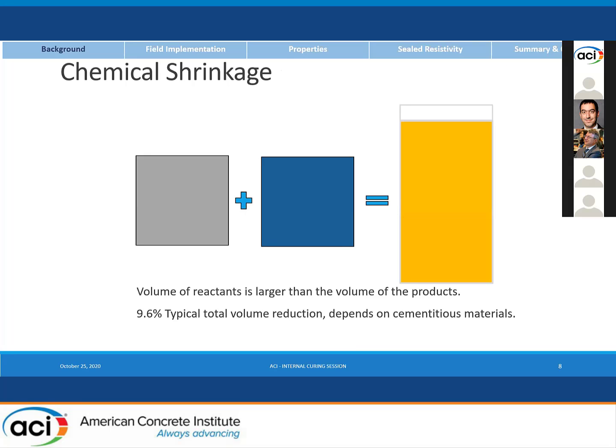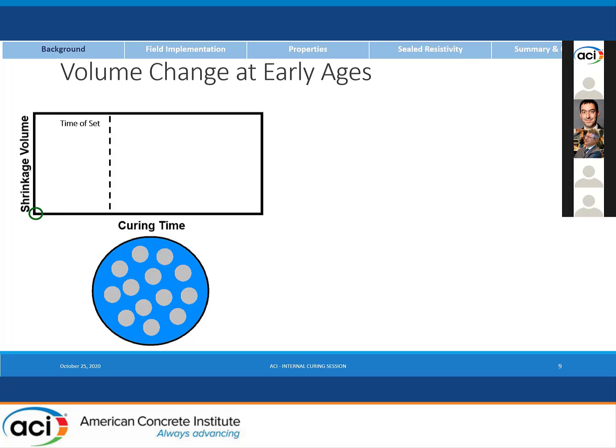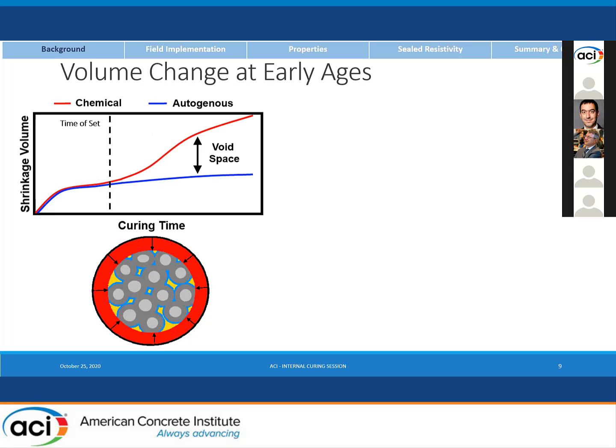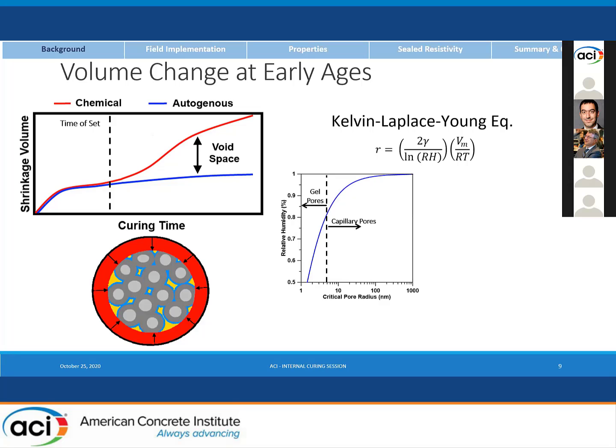So very briefly, the internal curing is really coming from a requirement of the fact that we have chemical shrinkage with the hydration of cement and water. So when you react cement with water, you get about a 9% volume reduction. When we look at this in a system that's hydrating, you'll measure this over time and you'll find that up to the time of set, the chemical shrinkage is exactly equal to the autogenous or bulk shrinkage. Thereafter, you actually measure a difference between those two values, and that is actually represented by void space creation. We can describe this using a fundamental relationship, and we find out that we are emptying out pores of smaller and smaller radii.